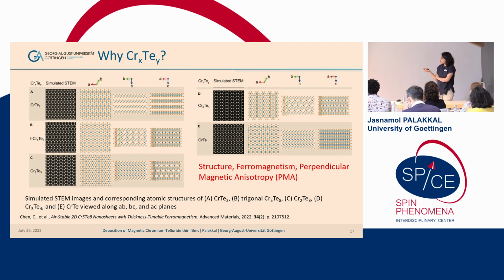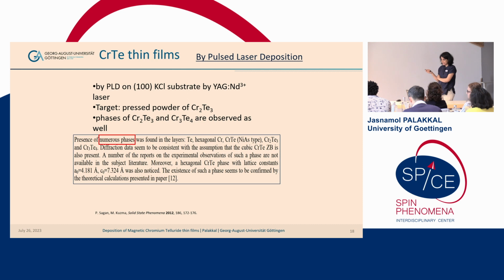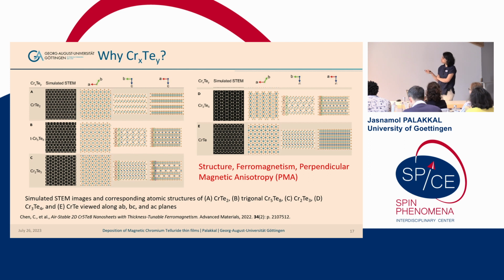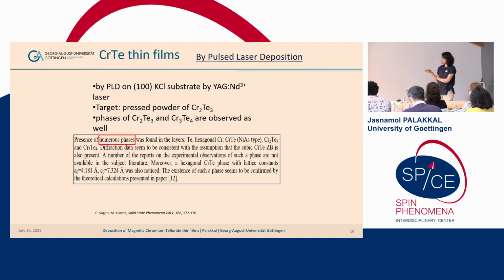So these 2 physical properties at room temperature can be easily combined for spintronic devices together with the other 2D material. But in that case, it's important to know if the origin of magnetism is really the lattice of this material, because depending upon the deposition technique or deposition conditions, or even depending upon the group who is growing this material, they are getting different magnetic properties, and that's not nice. And that's why we would like to investigate this material, carefully controlling the defects in this material, and also by adjusting the ratio between chromium and tellurium.